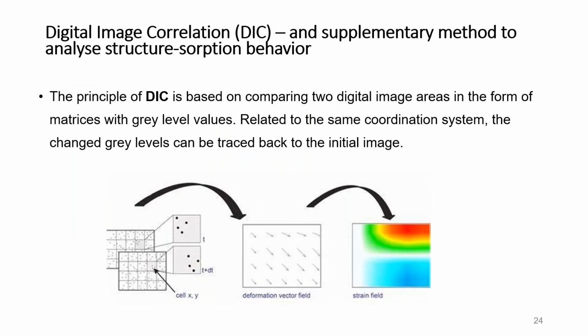So that's the one I have already mentioned, but if you want to know the within tissue movements during sorption, digital image correlation is a very good supplementary method that you could add to a DVS that has a good camera built in. Because you need to be able to recognize a pattern at the surface, but the wood structure gives you enough pattern to get picked up. So when there is movement, thinking back on the little movie I was showing, the digital image correlation can give you stress and strain pictures and analysis.